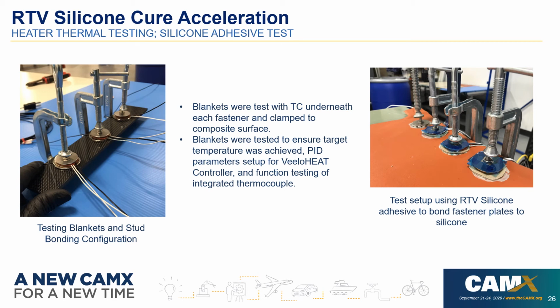Next, we tested our configuration to validate the concept. First, we placed a second thermocouple underneath the fastener and the blanket to test the surface temperature, and then we clamped the stud and blanket to the carbon plate. The blankets were tested to ensure that the target temperature was achieved. During this process, using our controller, we were also able to set the PID parameters and perform function testing of the integrated thermocouple.